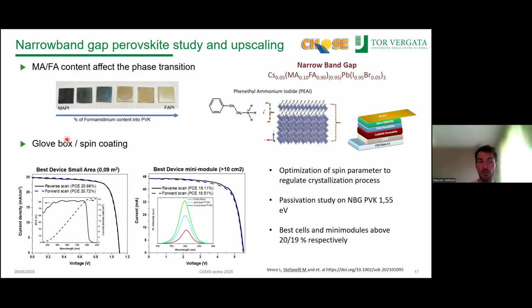As usual, we start with the glove box spin coating way, and the perovskite that we use in this case is a narrow bandgap 1.55 eV with 5% of cesium and 10% of methylammonium. We also implemented the passivation strategy here on top of the 3D perovskite. And with this kind of system, optimizing all the parameters in order to get a good crystallization of our perovskite layer, we got the best efficiency in a small area above 20%, and for the best mini module above 19%, respectively.